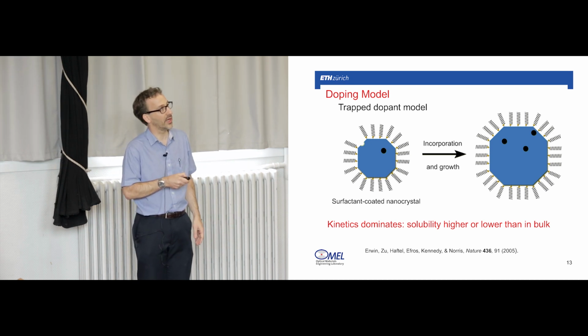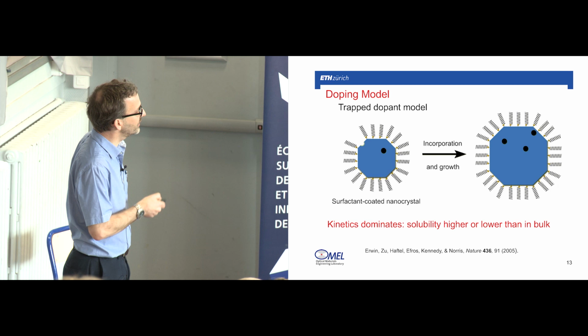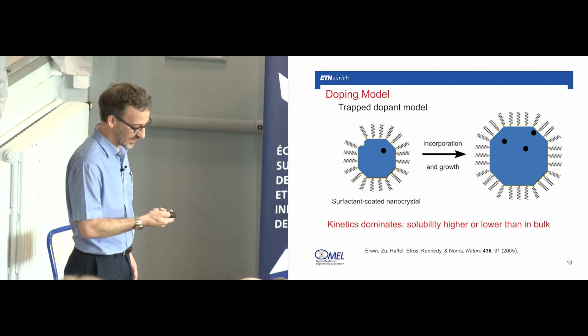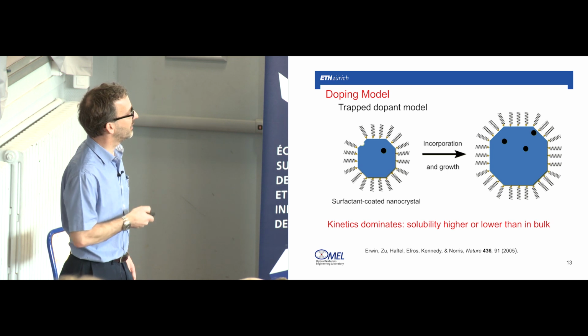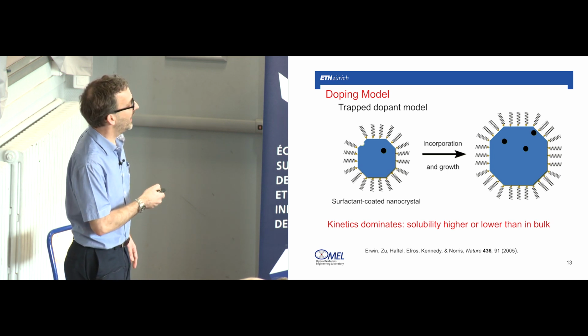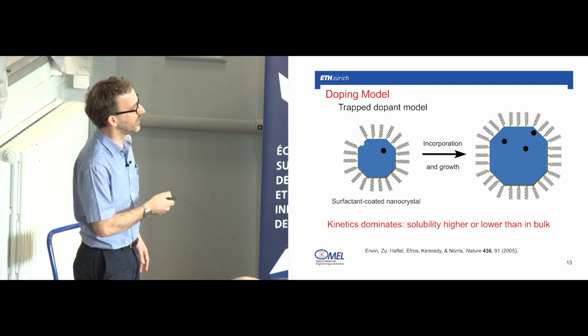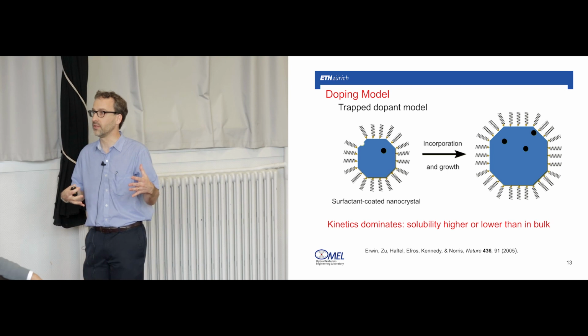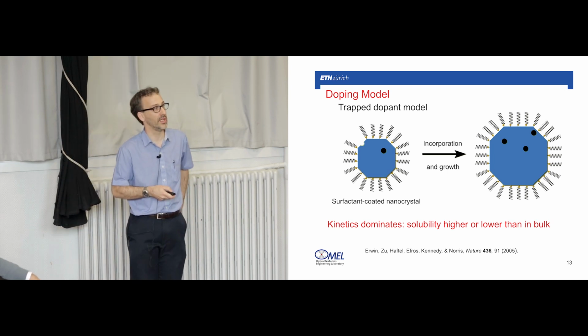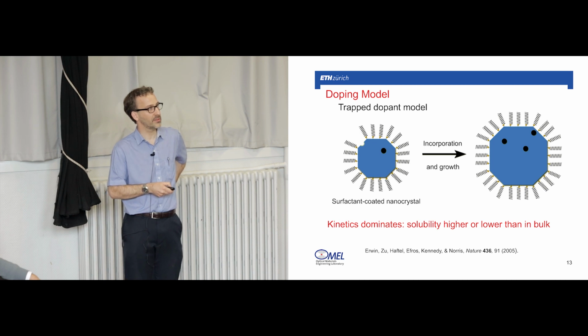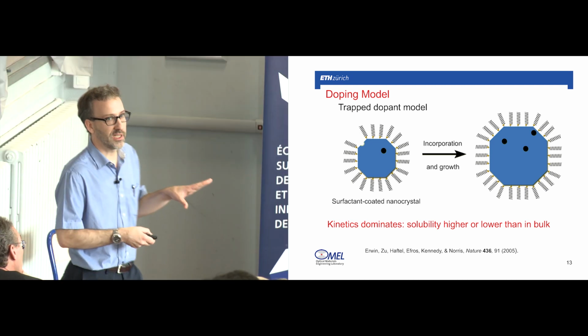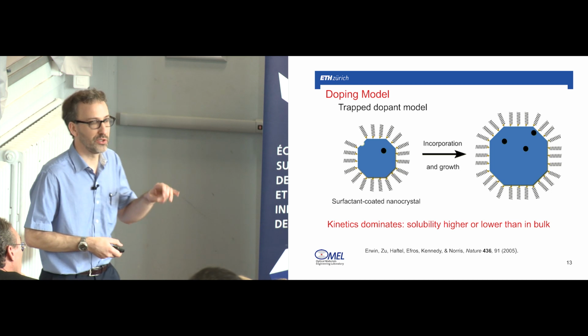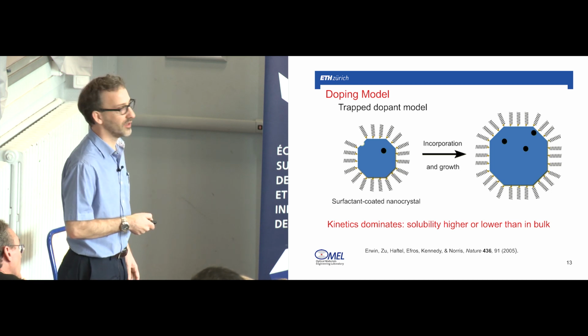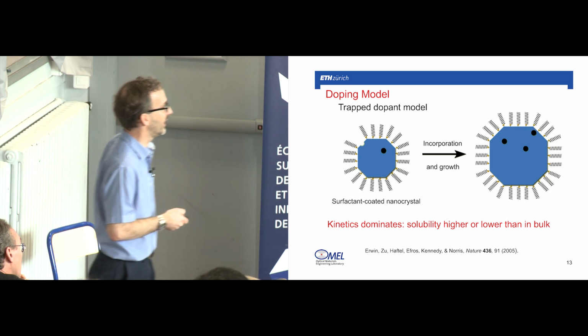If you want to get an impurity into this growing nanocrystal, there are several things that you require. Of course it's surfactant coated, but to grow, we know that the surfactant has to be popping on and off. And so our impurity atom can come in, in this cartoon, and stick to the surface. And if it stays there long enough, then it can be overcoated with more material. If diffusion is not active in this limit, then it's basically going to be stuck where it is inside the nanocrystal. So in this model, the kinetics really dominates the doping. And it's interesting to think that, just like molecular beam epitaxy, this would imply that the solubility of the dopants can be either higher or lower in principle than in the bulk, because kinetics is in control, not thermodynamics.